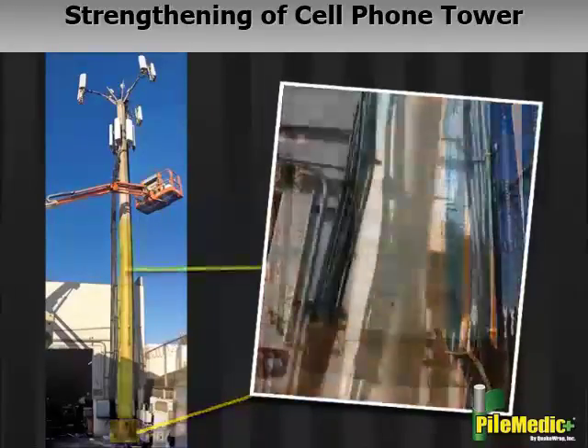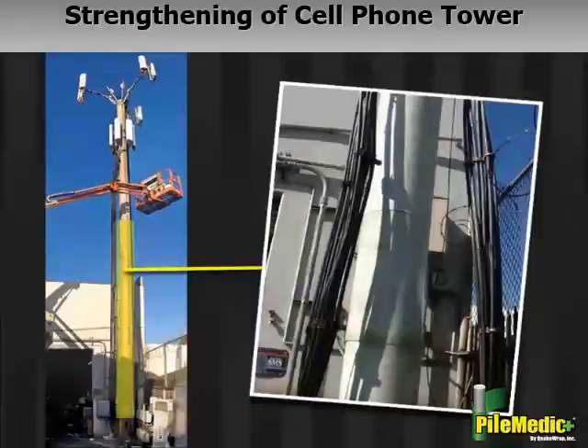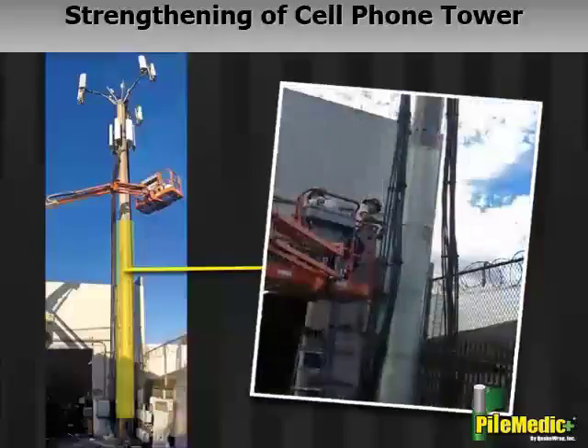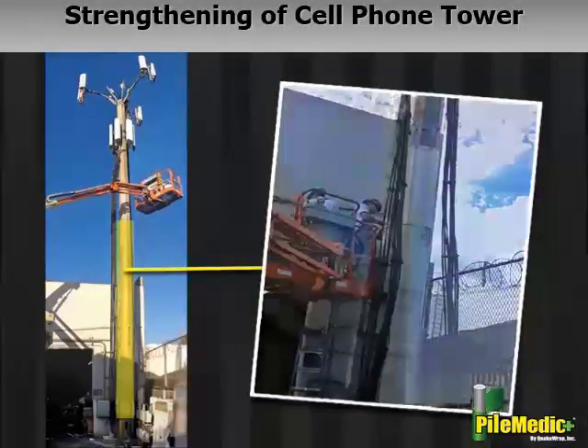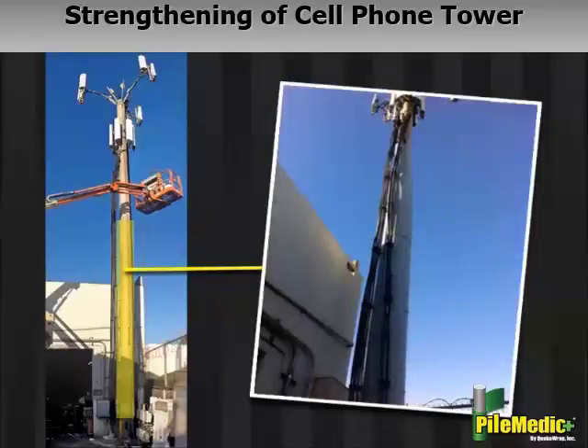6. Several PileMedic jackets were used to create a shell with an annular space of 1.5 inches, or 38 millimeters, from the height of 4 feet, or 1.2 meters, to a height of 16 feet, or 4.9 meters. This region was also filled with an expansive non-shrink grout.